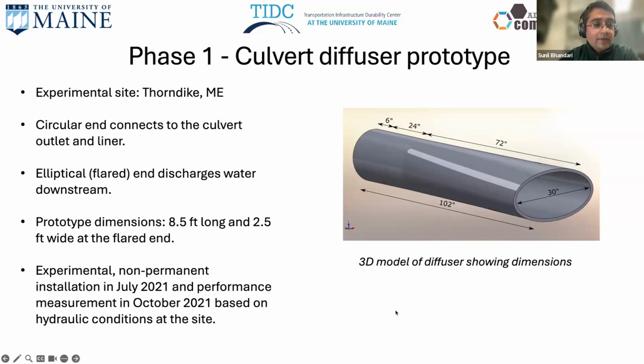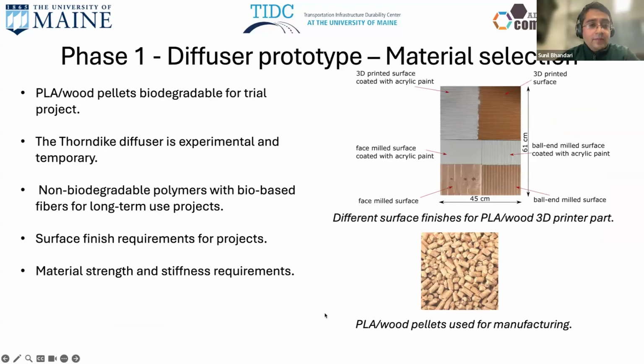This was an experimental non-permanent installation that was installed in July 2021, and the measurement of the flow was made in October 2021 based on the hydraulic condition at site. So for phase 1 material selection, we used PLA wood pellets, which is a biodegradable material for this trial project. The diffuser was experimental and temporary, so we used bio-based material. For long-term use projects, we would go with non-biodegradable polymers.